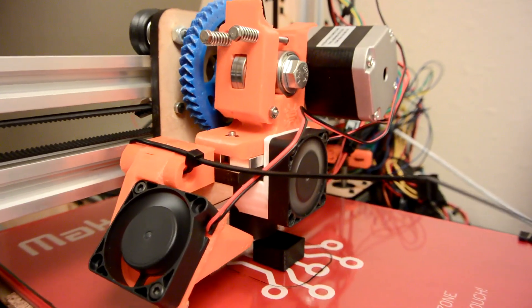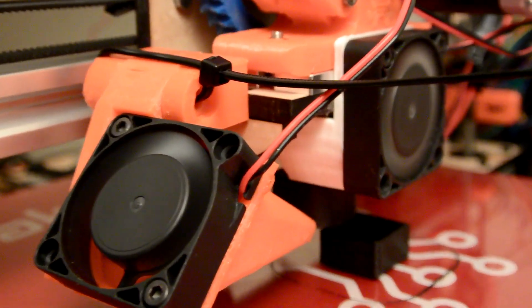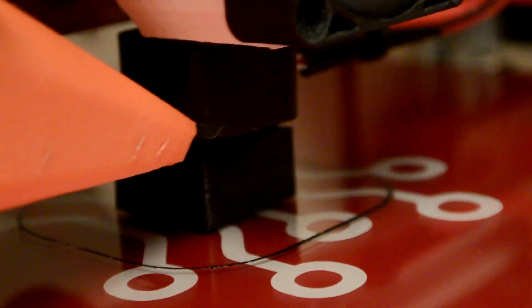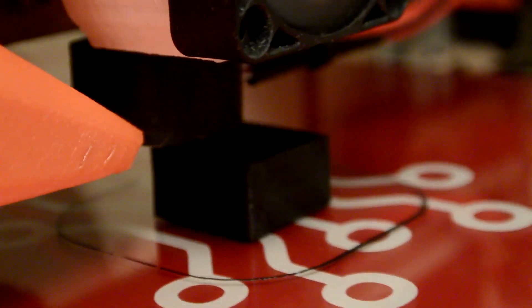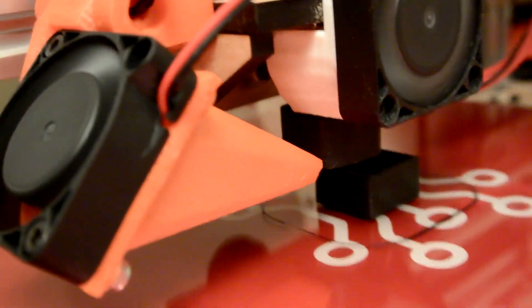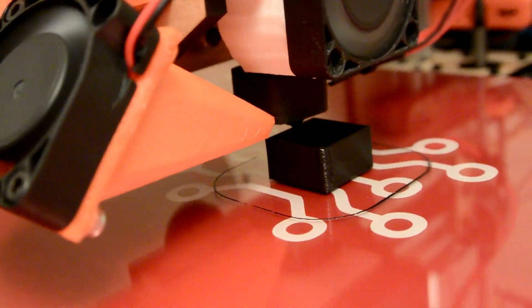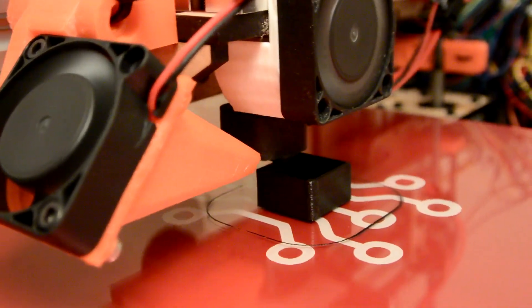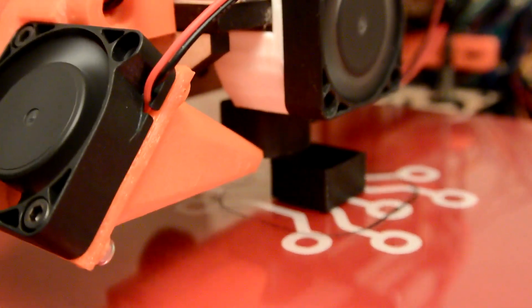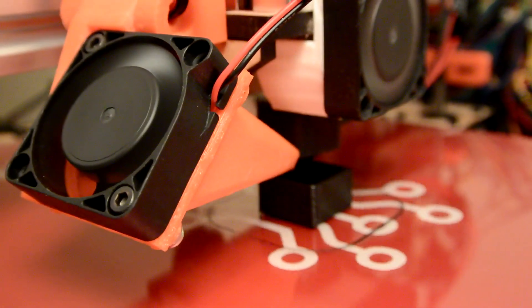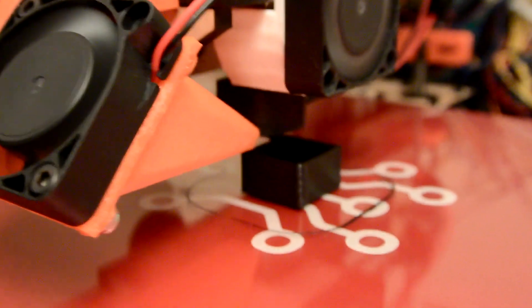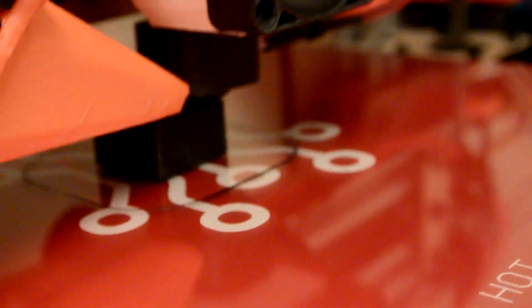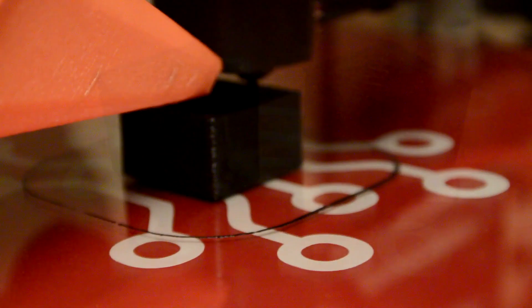So here's the first print with the fan going. You can see I have the fan all hooked up, and it's all connected. And I'm just printing another calibration cube using some of the Filaflex. And I really think that the fan is going to help the quality of this print dramatically. So we'll have to wait, of course, until this finishes, and I can compare it to my other calibration cubes. But you can see that it's currently blowing on the print. I have Slicer set up so that if the layer time is under 30 seconds, then the fan's on full blast. And if it's under 60 seconds, it's kind of on, but with a certain percentage. But since these are really small layers, the fan's just blowing full blast.